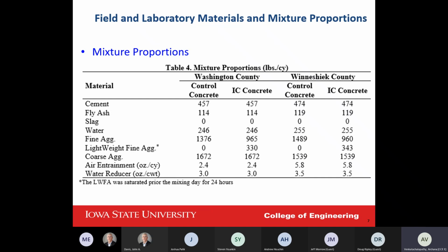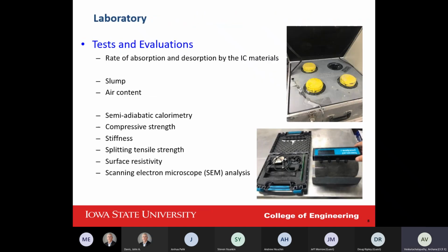And it's just 15% to 25% based on the volume, not the weight, because it's much lighter, of the fine aggregate, to just keep the strength, because the fine aggregate keeps the strength. And also the lightweight does not have the capacity and capability of the regular fine aggregate to strengthen the concrete, but it just increases the hydration rate. That's why we keep it at 15 to 25% volume-wise replacement. So in this way, we can keep both of them.